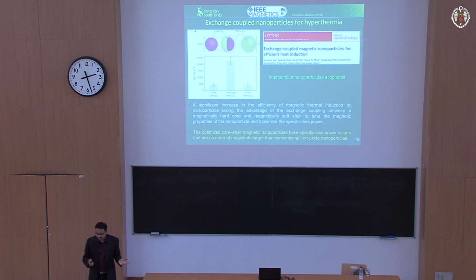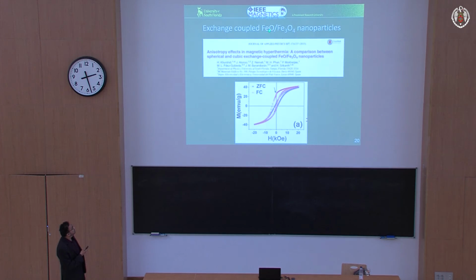coupled nanoparticles. So one of the postdocs in my group, Hafsa Khurshid, she took up this challenge and she made these particles, FeO, Fe3O4. We had the shell as Fe3O4, so it's completely biocompatible, it's well known, and FeO inside. FeO is a lesser known iron oxide phase, it is the Wüstite phase. And guess what? It's antiferromagnetic. By the way, there is a group in Spain that is studying these structures also in Barcelona. Professor Josep Nogués and his group has been looking at this too.